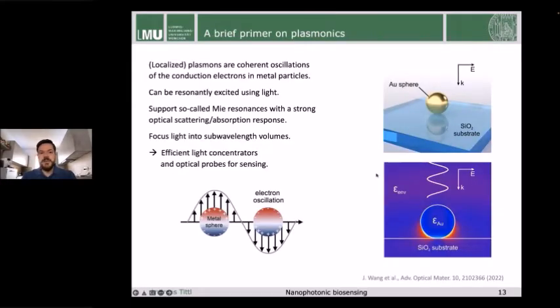And just a very, very brief primer, because we will be using these nano resonators a lot. If you think about, for example, a gold sphere, you can excite this with incident light and drive a resonant excitation of the conduction electrons in the metal particle. And this can be used to concentrate the light and lead to very high field enhancement. So we have efficient light concentrators, and this makes them great optical probes for sensing.